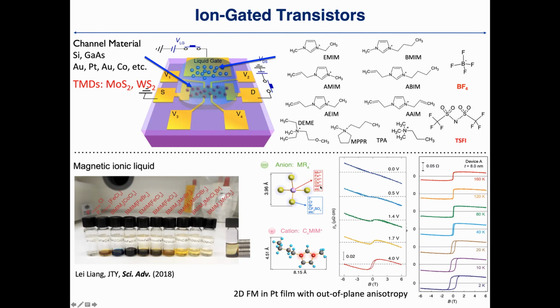With this, we can actually gate and control the concentration of these ions on the surface. So we take non-magnetic platinum, and then we gate with this technique. We can actually induce a ferromagnetic state, as we can see here. If you increase the gate voltage, we start to see an anomalous Hall effect and a coercive field. And in this particular 8 nanometer system, the hysteresis loop can be quite large. Considering the field-induced mechanism, the very, very large carrier density and the very short screening length, this modification should be concentrated right at the surface. So this should be a 2D ferromagnetic system, and the anisotropy is out of the plane.